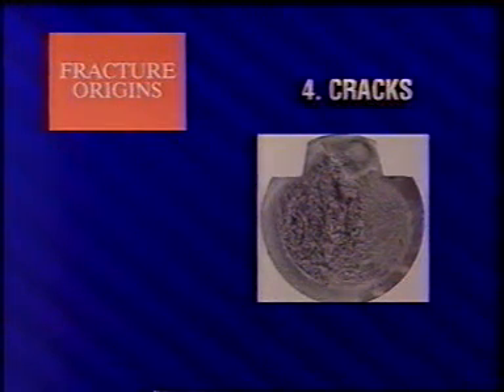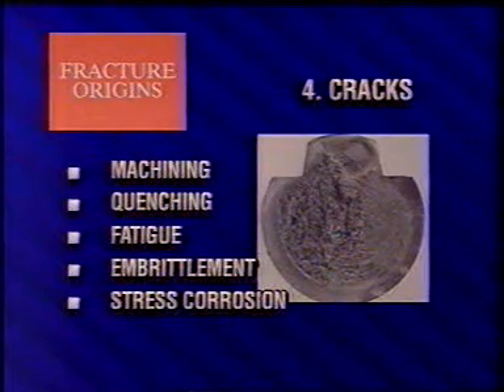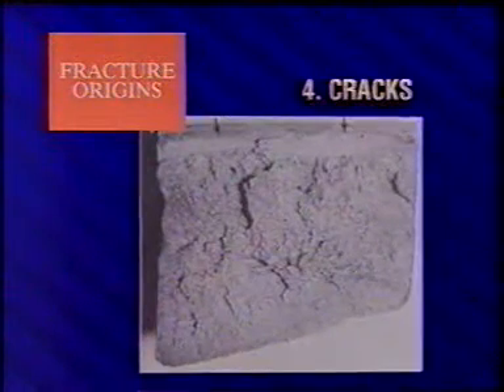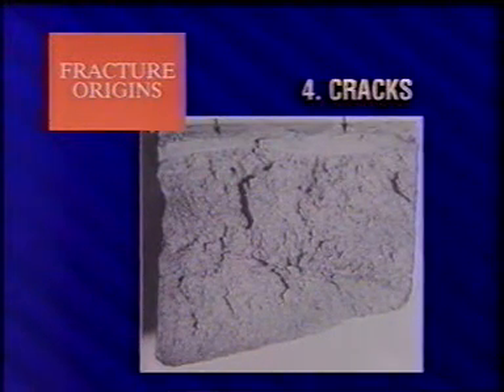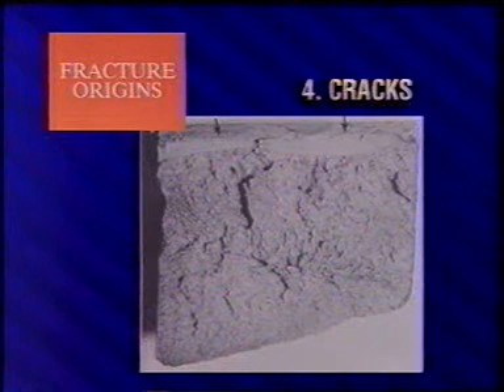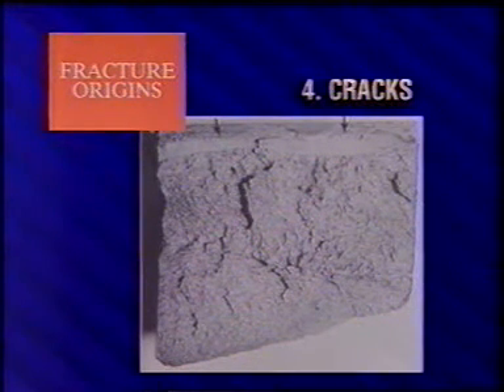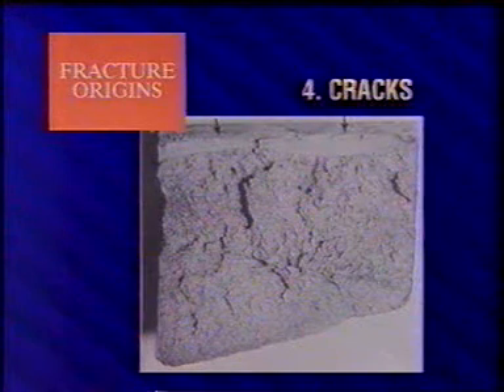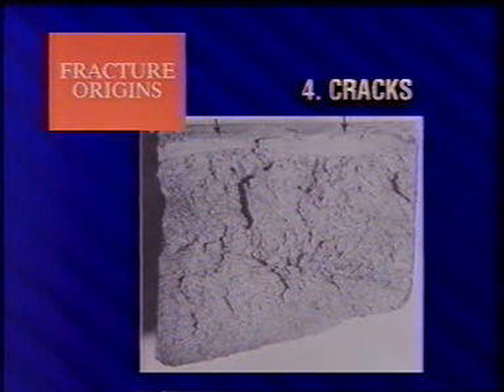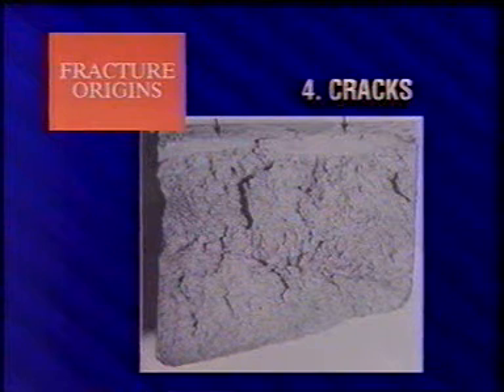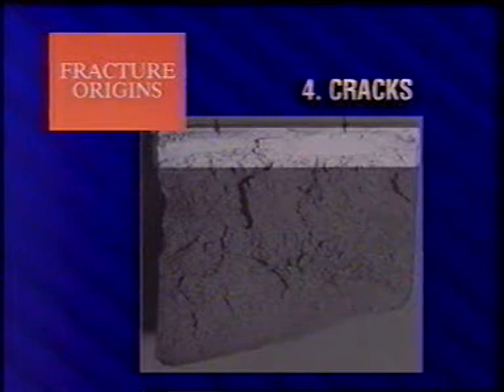Fourth, cracks resulting from machining, quenching, fatigue, hydrogen embrittlement, liquid metal embrittlement, or stress corrosion also lead to brittle fracture. In fact, the single most prevalent initiator of brittle fracture is the fatigue crack. The fatigue crack accounts for at least 50% of all brittle fractures in manufactured products, and this is a conservative estimate. The fracture surface of an ASTM A36 structural steel member shows this failure began with a fatigue crack, which progressed only a short distance before brittle fracture occurred.